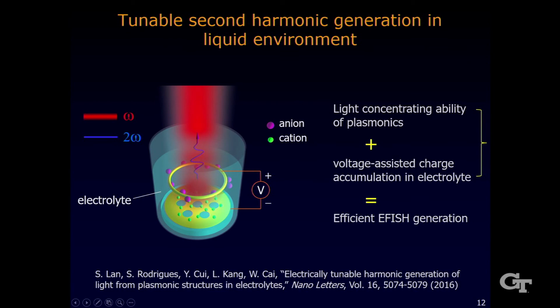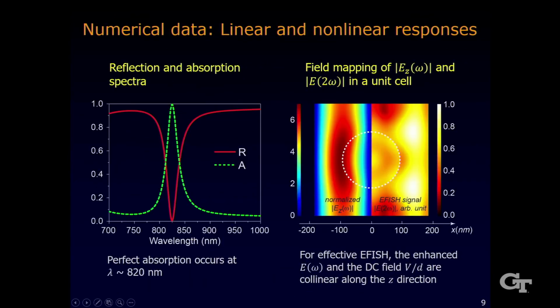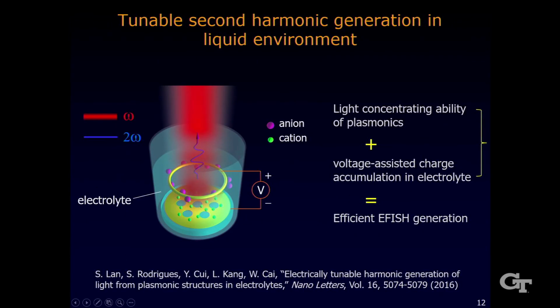So other than solid state systems, the electric field controlled harmonic generation can also occur in liquid environment, especially in some electrolyte. Because other than applying voltage across a tiny gap, as you have seen in the previous demonstration, the strong electric field can also occur if there's a surface charge present on the metallic surface. This is a direct consequence of a boundary condition of Maxwell's equation, right? If you have a rho s, you are going to have a very strong D normal around that surface,